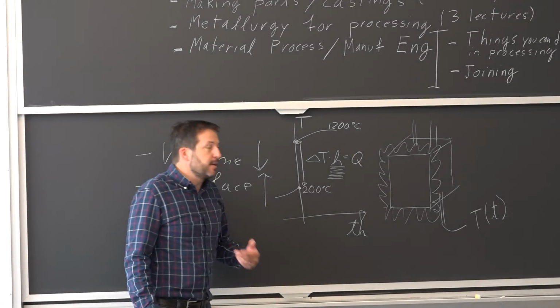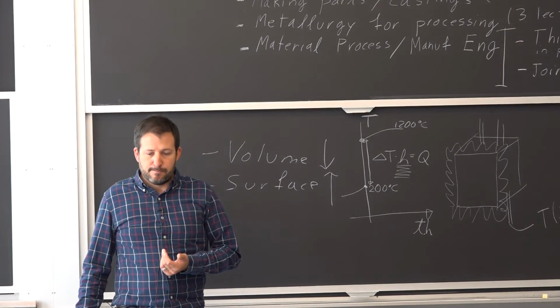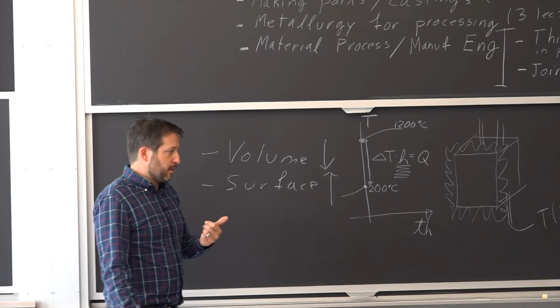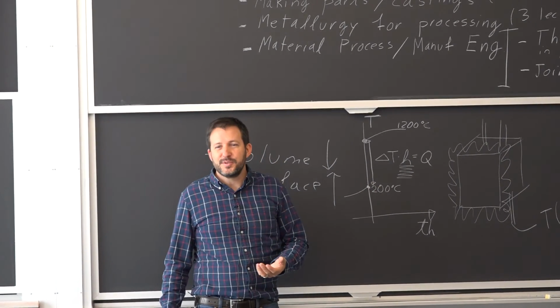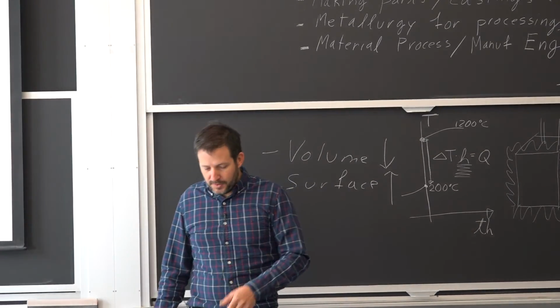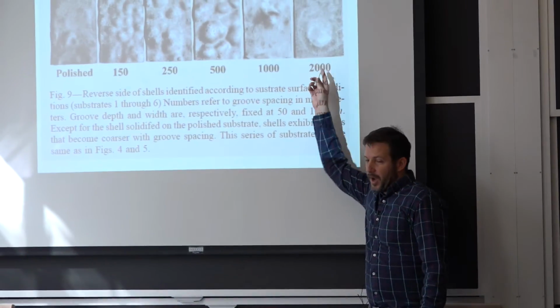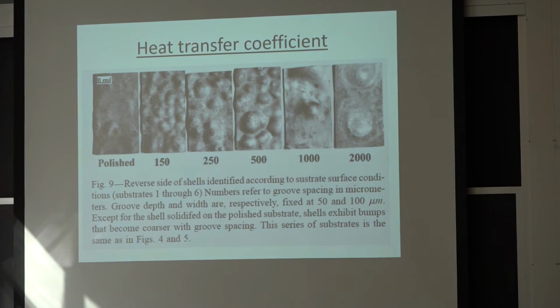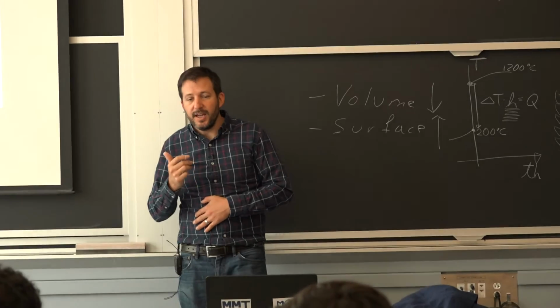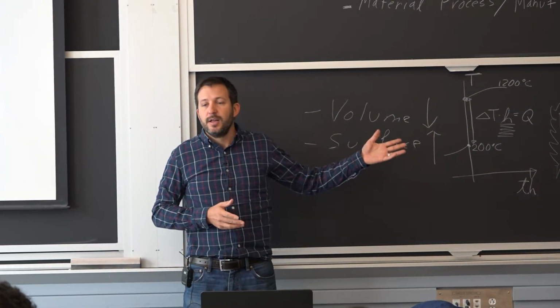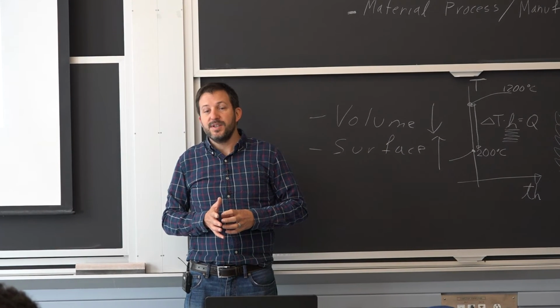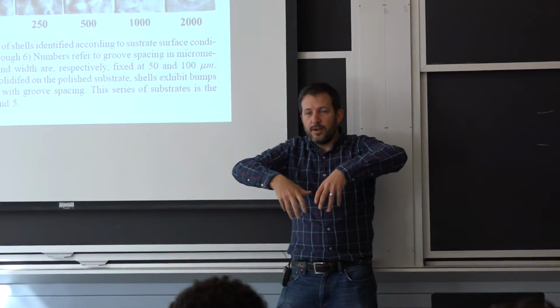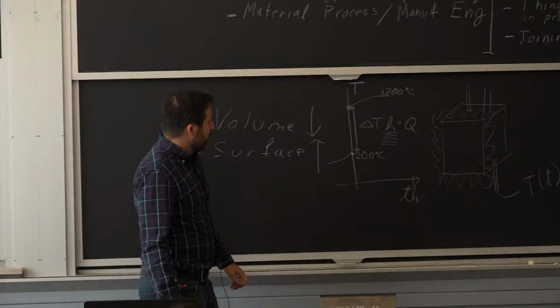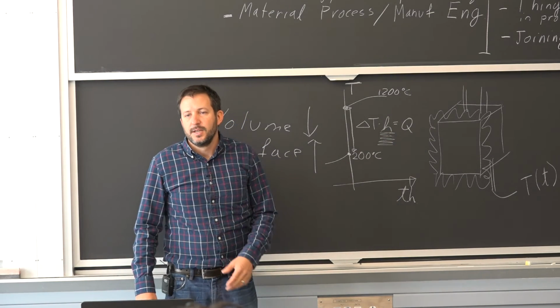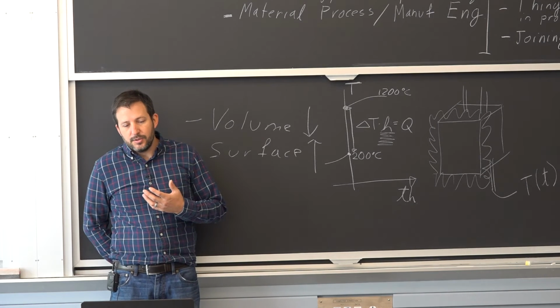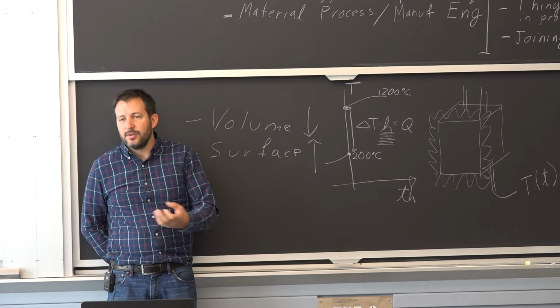So the two things that we've talked about so far for casting is nucleation. And then here, this is a second concept, is you have to transfer the heat. When you start to solidify, you have to transfer the heat. And if you have these big bumps like this, I used the argument that I didn't want a bump to come against the other bump, but that's not the only reason why I don't want big bumps. If I have these big bumps, all of a sudden the shell that I'm creating is deforming physically. So you'll have a contact here where you started, and all the surrounding area is going to bow and not touch. And it reduces my heat transfer coefficient on the interface. So there's so many reasons why you really want to try to get a good contact between your metal and the mold and keep it regular.